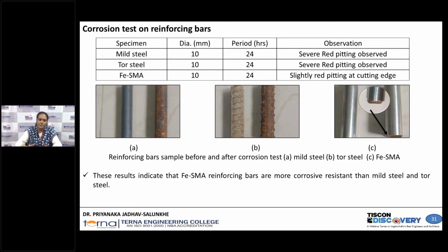If you see the figures, figure A is for the mild steel, and here the method we used was the salt spray, with 3% concentration, and the period of this test was 24 hours. Figure A shows this mild steel fully corroded. This Tor steel also fully corroded. It is showing huge red pitting on the surface.